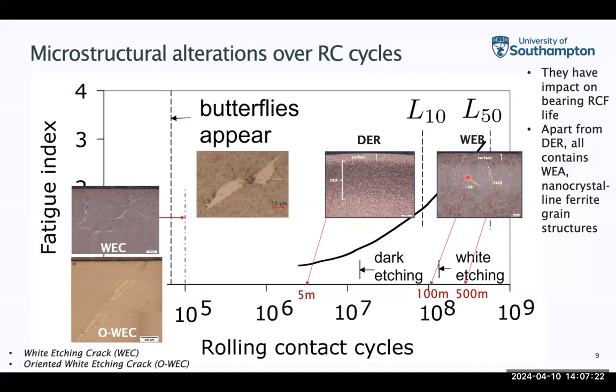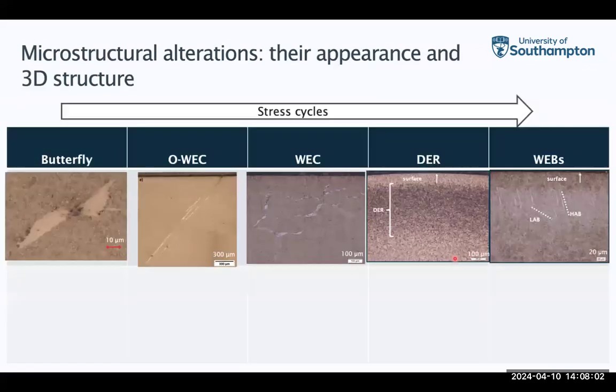So if you look at them, they all have these white structures in these features. These features appear white because they have what we call nanocrystalline ferrite grains, which are very small grains and harder than the surrounding matrix or the steel structure. So when you polish them and etch them, they remain as very strong material. They are not etched away. So that's why they appear white under the optical lights. So I'm going to focus on these structures for the rest of the talk.